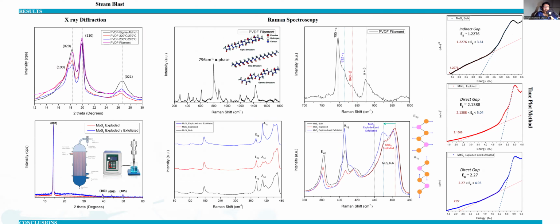So for molybdenum disulfide, XRD patterns confirm the hexagonal phase of the material. We have both the material exploded with the steam explosion process, and the material exploded with the steam explosion process and then exfoliated with ultrasonic exfoliation. So we have these two ways of preparing our material, and we already see that we have our predominant phases of molybdenum disulfide. Also, by applying the explosion and exfoliation process, we already have a non-contaminated molybdenum disulfide. We have the hexagonal phase with peak broadening indicating reduced layer thickness.